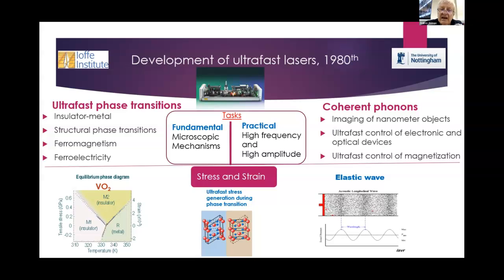I would say that's what my talk is about: stress, which is also related to strain. Even in equilibrium, if we consider phase transition in equilibrium, say for vanadium dioxide, the temperature of phase transition, which is slightly above room temperature, depends on the strain.